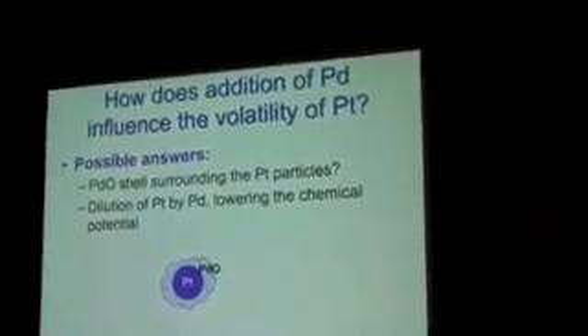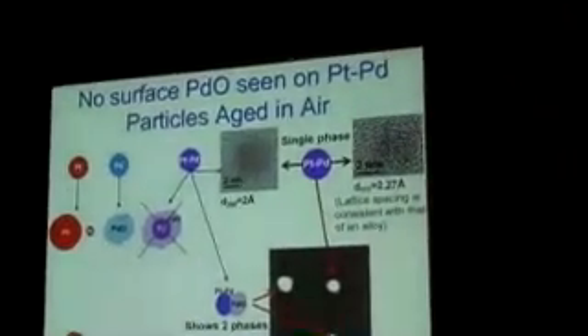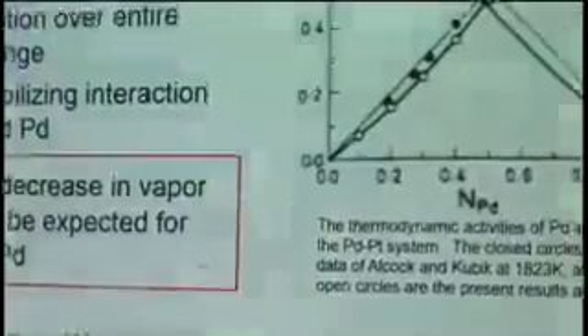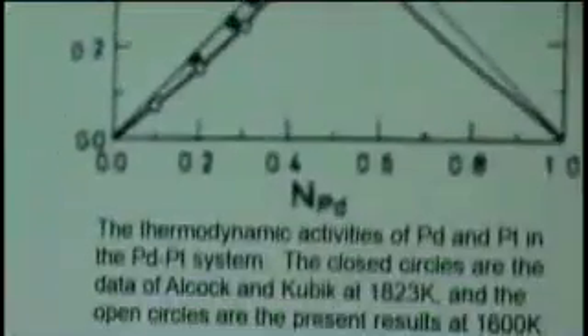It could be possible that it forms a shell, but it doesn't. I showed you that here there's no such structure. So what really is going on is you form the bimetallic. Sometimes there's room for a phase segregation, but by and large you have a metallic platinum palladium alloy. And why does it have a lower vapor pressure? It's Raoult's law. The solution is not ideal, but the deviation from ideality is very small. So 50-50 platinum palladium would have a 50% reduction in the rate of emission.